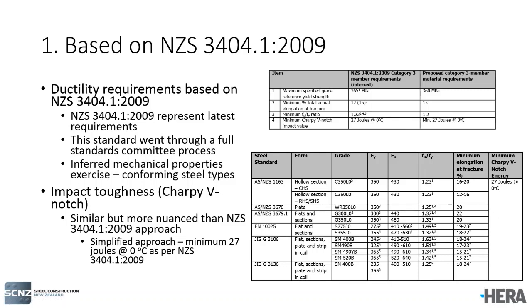If you look at the ductility requirements, here I've tabulated them just to compare them. This is the maximum specified grade, reference grade. If you go through the list of all the conforming steel grades, 365 MPa was the maximum. This was for a Japanese steel grade, an SM520B or 490YB, which was 365. We're proposing 360. If you look at the minimum elongation at fracture values from the conforming steel types, you'll notice that for the RHS and the SHS sections, it was as low as 12%. The value that I've noted in brackets is saying that if you look at the circular hollow sections and all the other various plate and section standards, the lowest value that you'll find is 15%, and we've gone for 15%.